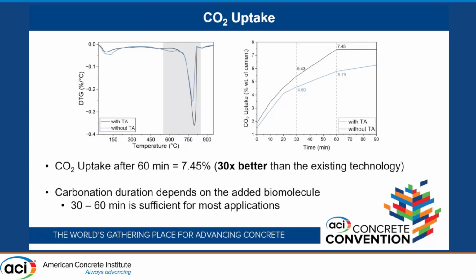Besides that, the biomolecule will also facilitate the CO2 uptake. Right now, after 60 minutes, we are almost at 8% of the cement weight in CO2 absorption, which is over 30 times better than what's being done right now. So you see a much higher CO2 absorption efficiency. And you can also shorten the time, because remember, we're trying to make this something that's applicable, so we're trying to shorten that time. Usually 30 to 60 minutes is more than enough for you to have good performance.